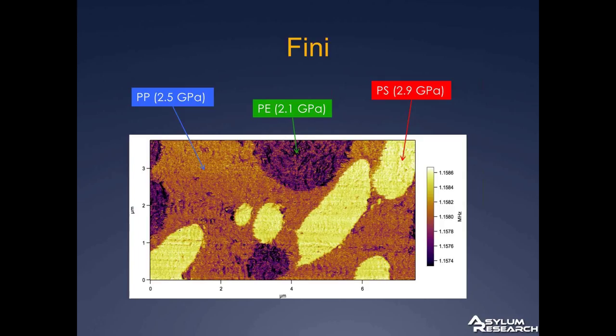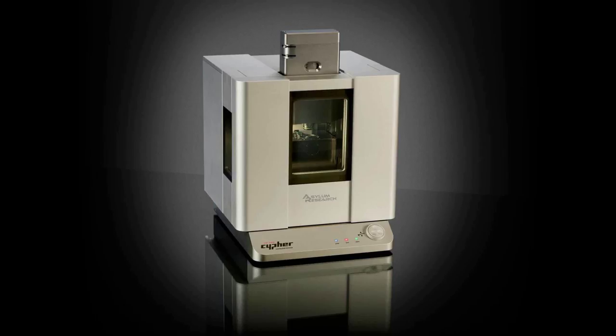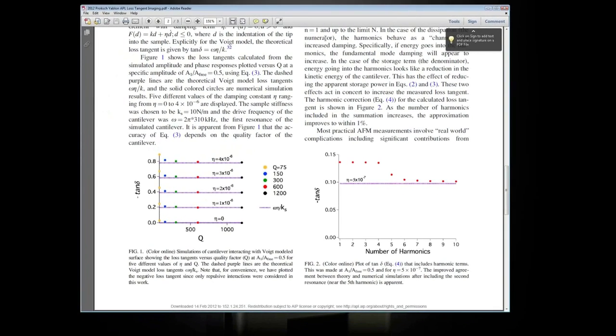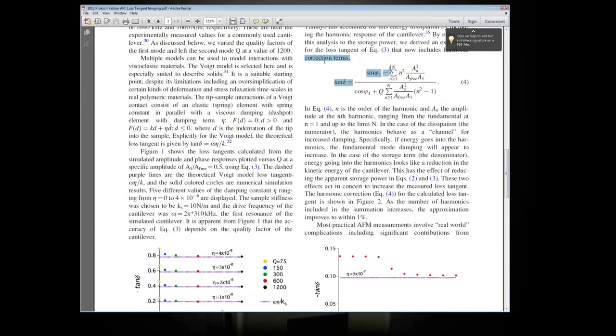Yeah, so we've had a couple questions on this subject. Basically, I think it boils down to when you impact the surface in tapping mode, you're exciting more than just that fundamental frequency. You're exciting a range of frequencies. This is from the paper on loss tangent imaging. This expression at the top, equation number 4, includes the effect of the higher harmonics. So we actually do account for the energy, both the energy stored and the energy lost in those higher harmonics.